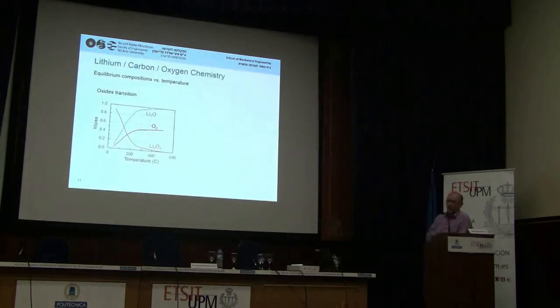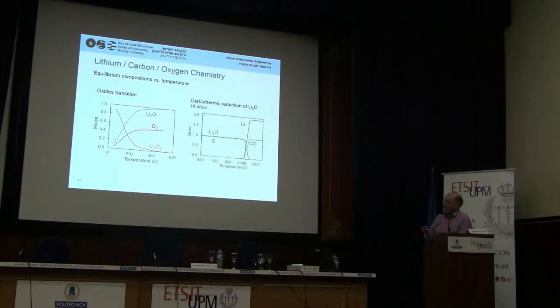Okay, so if we take the lithium oxides, we have two stages in the heating. First of all, at around room temperature, most of the oxide is in this form, lithium peroxide. When we heat to about 400 degrees, oxygen is released and the peroxide becomes lithium oxide, and then we need to continue heating until it is decomposed. If again we add carbon to the mix, then around this temperature, 1100 C, the lithium oxide and carbon react, the lithium is released and the carbon takes the oxygen and becomes carbon monoxide, similar to the same process that I showed before with zinc oxide.